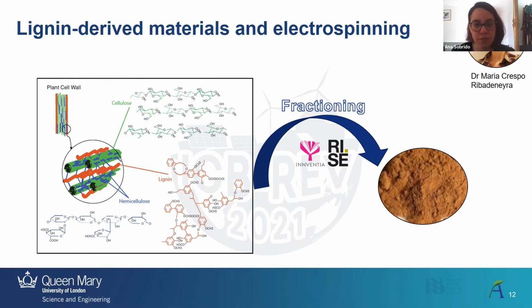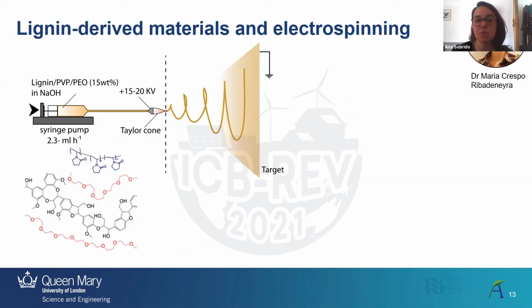After all the fractioning and all the processing to obtain the cellulose, they end up with this powder that you see here, which is the lignin. So that's what they send us. And what we do with that is put it in the syringe, and then with this NaOH solvent and another copolymer, although now we have developed a method where we don't even need to add any copolymer, just with lignin, we're able to form the fibers.